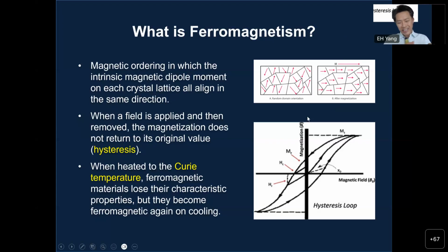Now, if you heat this material above the Curie temperature, then the ferromagnetism disappears from the material. But you regain the ferromagnetism upon cooling, which means that you better have a high Curie temperature, right, room temperature or higher. Otherwise, you need to put your material in the refrigerator to get the ferromagnetism there, right?